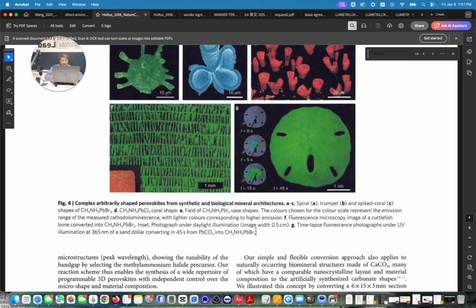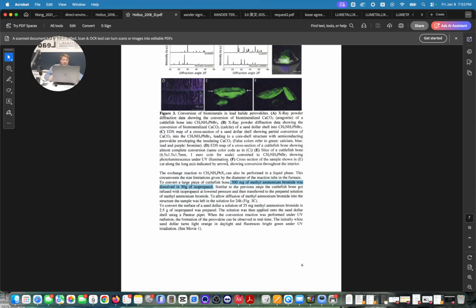It says that time-lapse fluorescent photography under UV illumination at 365 nanometers of a sand dollar, converting in 45 seconds from lead carbonate into methylammonium lead bromide. Now, what's the reagent? Because we know that this is methylammonium lead bromide, which you would get from contacting methylammonium bromide with the surface. Luckily, they were so kind as to give us the exact recipe in this paper.